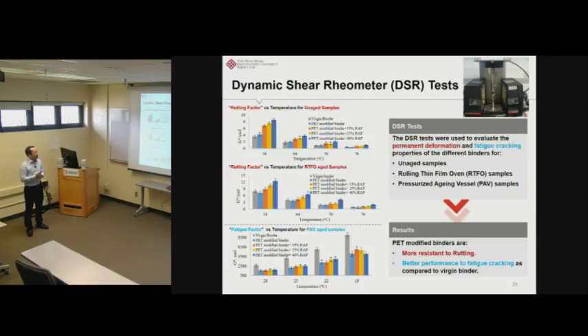Then we also conducted the DSR test to check its rutting performance and the fatigue performance. We all know that by doing the DSR test, we can get two important factors. One is the rutting factor, one is the fatigue factor. For the rutting factor, we have done tests on both the unaged binders and the RTFO aged binders. In these two plots, the first column is always the virgin binder, and the second one is the PET modified binder, and the following are the PET modified binder with increasing amounts of RAP binder.